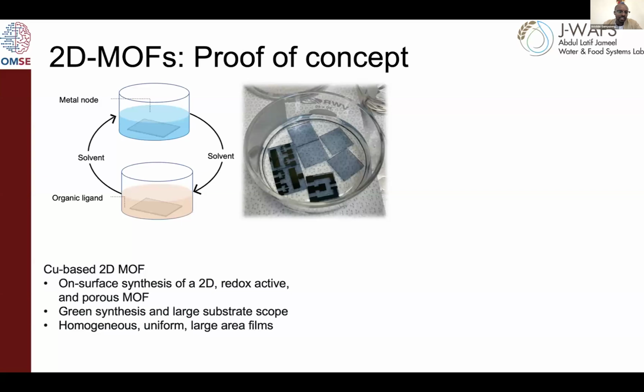So the first thing we wanted to do was actually show that we can make these materials into thin films, because this tends to be challenging. For Tim's system, for the polymer, you can make a solution and cast it on a substrate. But for these metal organic frameworks, usually you synthesize them as a powder. So for us, we had to investigate how to grow these materials into thin films onto electrodes. So we can do this with a solvothermal method, where we do the metal and ligand sequential dipping of a substrate, and we can grow these films at actually quite high quality, and it's very robust.